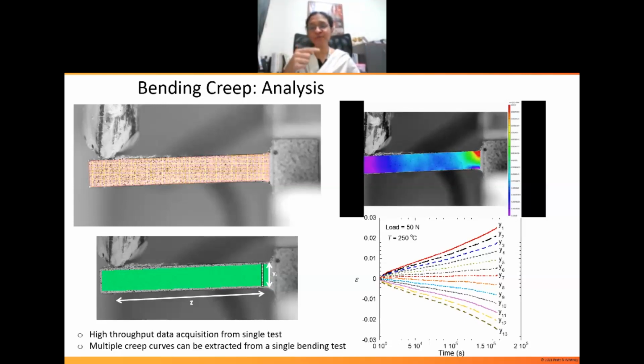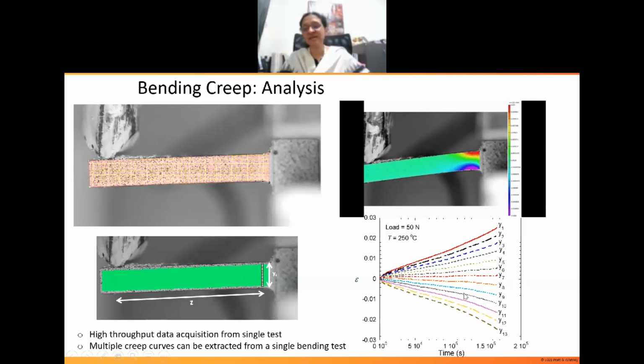And the beauty of this technique, I won't go into the details, is you get tension-compression data from a single bending creep specimen. No need to do a compression test or tensile test. So for those materials with tension-compression asymmetry also, we're able to decipher this.